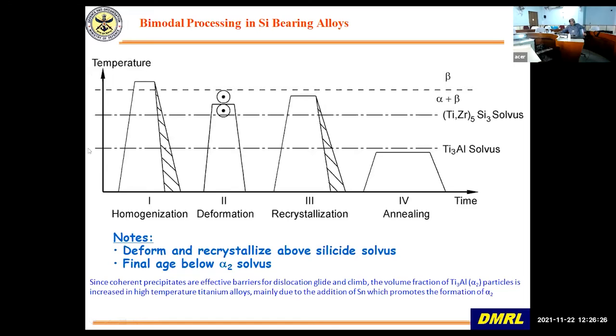So the first step is the homogenization. This I need not talk about. I have already talked about it, high up in the beta regime. And then if you want a bimodal structure, why you want a bimodal structure I will show you shortly, you do alpha beta deformation, and that is above the silicide solvus. It cannot be very low. Why higher? Because if you have already formed silicide, then the material will start cracking, because silicide is brittle. And then you anneal or recrystallize it slightly higher than the deformation temperature. And then final annealing and aging is below all the solvuses. So finally, you precipitate out all the Ti3Al as well as silicide to improve the properties. This is how high temperature near alpha titanium alloys are processed.